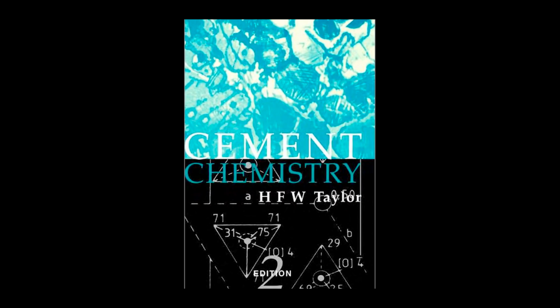It is. It's vital for you to understand that non-evaporable water is not the same as chemically bound water. Even at -79 degrees, the interlayer water within the CSH structure is still slowly being removed. So while it's a standard for measuring the extent of the reaction, it does slightly underestimate the total amount of water that's chemically incorporated into the crystal structures.